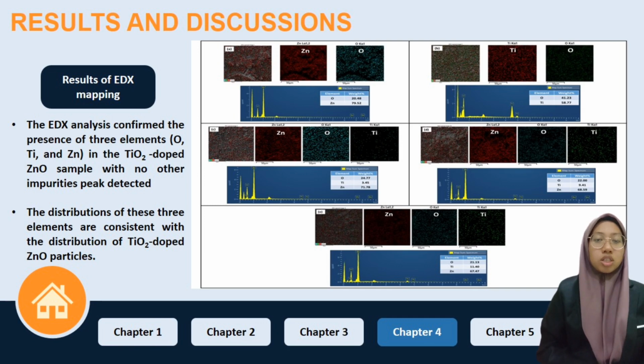Elements zinc, oxygen, and titanium show complete coverage of the image frame, and the titanium element was scattered homogeneously on the zinc structure. The titanium weight percent from EDX shows that the amount of titanium in the sample increased with increasing dopant concentration during synthesis, at 3.45%, 9.41%, and 11.40% for 5, 10, and 15 weight percent of titanium respectively.